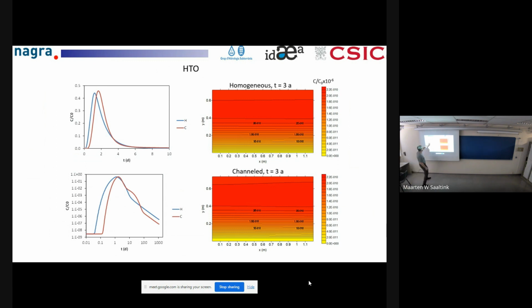The channel one has some retardation, yes, because you have diffusion into the fault gouge, which has high porosity, high diffusion coefficient. So it's much more effective in taking tracer out of the fracture than the rock matrix, which has small porosity, small diffusion coefficient. But that's the case here. It'll get more interesting.